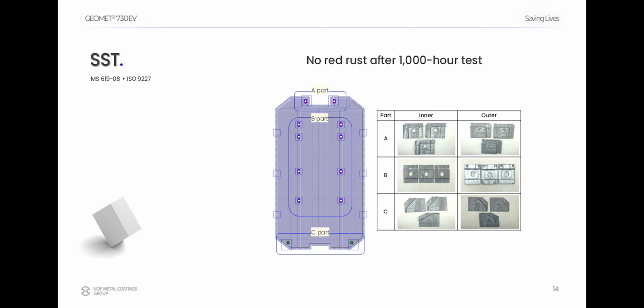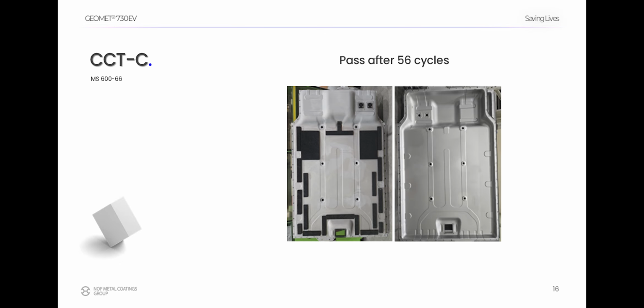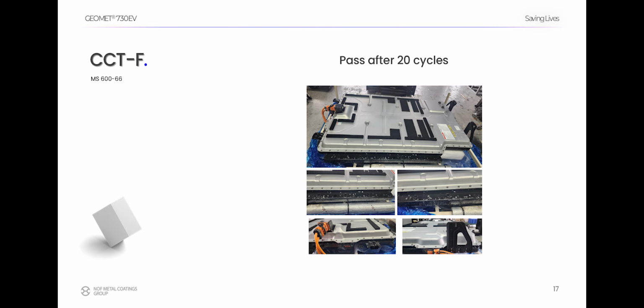For corrosion performance, it passed the salt spray test, CCTA, CCTC, and CCTF. CCTC is required for high-voltage EV battery cases. CCTF is required for HEV and PHEV battery cases. Both CCTC and CCTF are conducted on the fully assembled battery case after pilot line coating and battery pack assembly. So these results are closer to real production conditions.